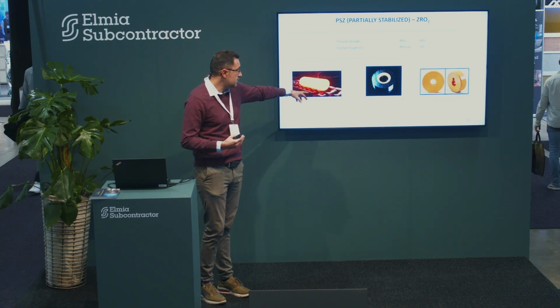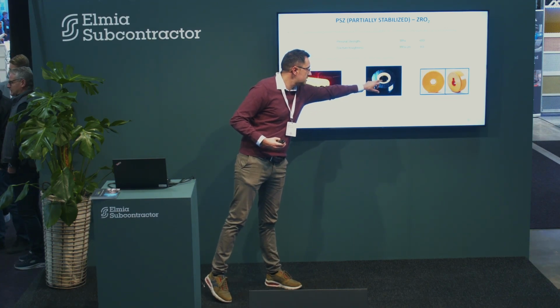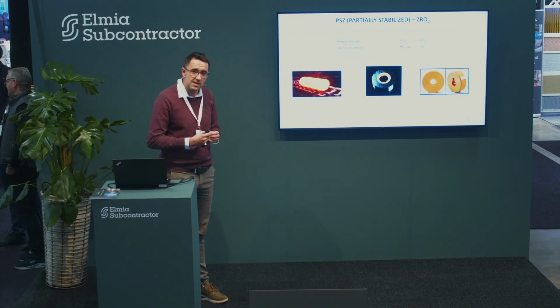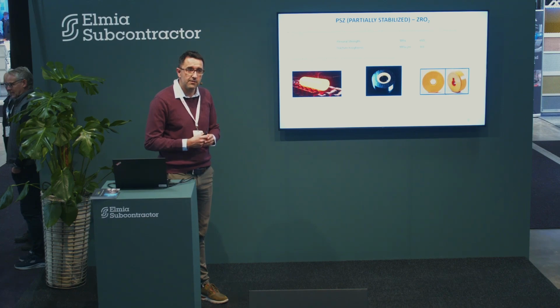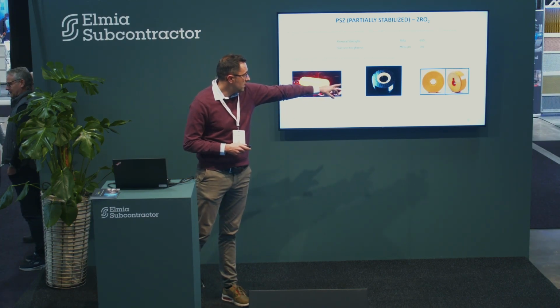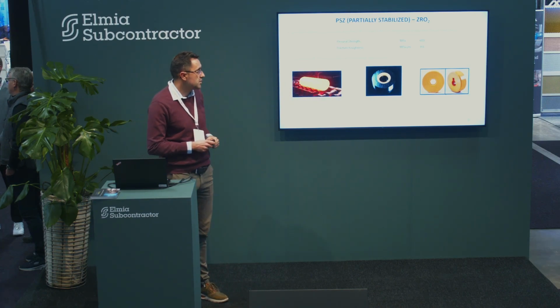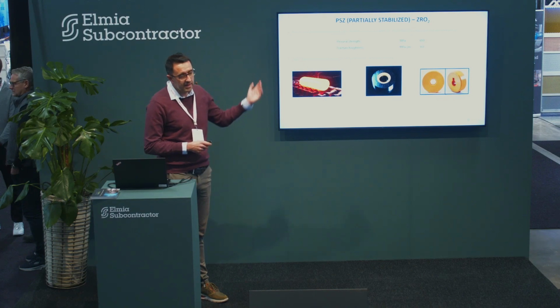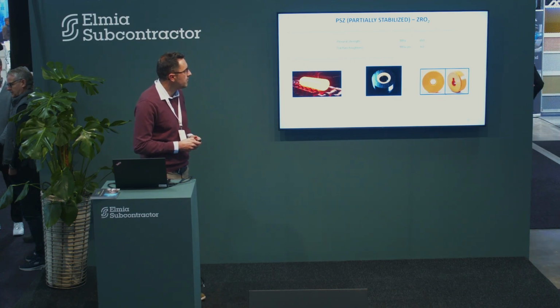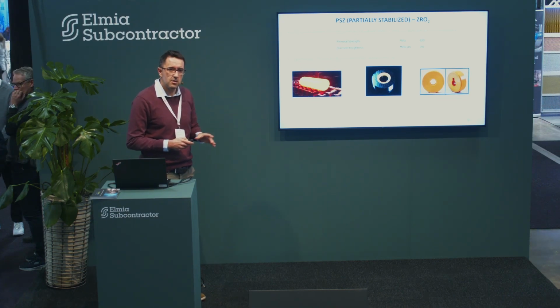This is an example of a bar, and this bar goes through the ceramic, which is shrink-fitted in a metallic case in order to resist the mechanical forces during the extrusion. Other examples of parts, also for the same application, for copper and copper alloy extrusion, can be produced in magnesia-stabilized zirconia, which is the material referenced here. So this is oxide ceramics, aluminium oxide, zirconium oxide.